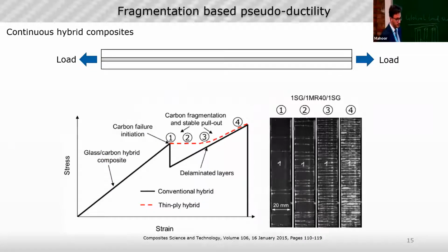And here comes the fragmentation. Fragmentation is one of the most common approaches used. It relies on the use of thin plies. Thin plies are very good at suppressing delaminations. They have low energy, they release low energy when they fracture, and the fragmentation is perfectly visible here, because hybrid composites also have this special feature, the translucency of the glass allows us to see what's going on inside. So we can see how the laminate fragments, we can see the damage, and that could also be useful for having a safe material as well.